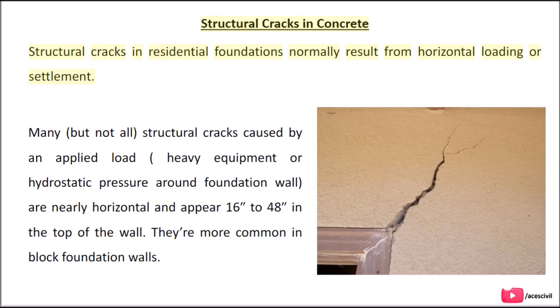Structural cracks in residential foundations normally result from horizontal loading or settlement. Many, but not all, structural cracks caused by an applied load — heavy equipment or hydrostatic pressure around the foundation wall — are nearly horizontal and appear 16 to 48 inches from the top of the wall. They are more common in block foundation walls.